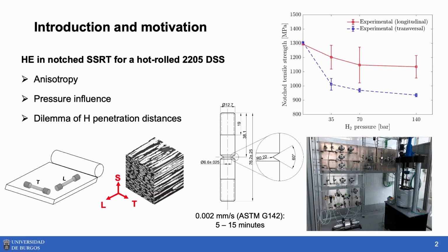You can see the experimental results that we are obtaining for those two orientations that we extract from the plate, longitudinal and transversal. Due to this anisotropy, we find that the reduction in the notched tensile stress, according to this standard, is stronger in the transverse direction. All of the tests are done in situ in this autoclave that we have in Burgos, integrated to a universal testing machine, with pure hydrogen. I can give you more details about the experimental facilities if you want.